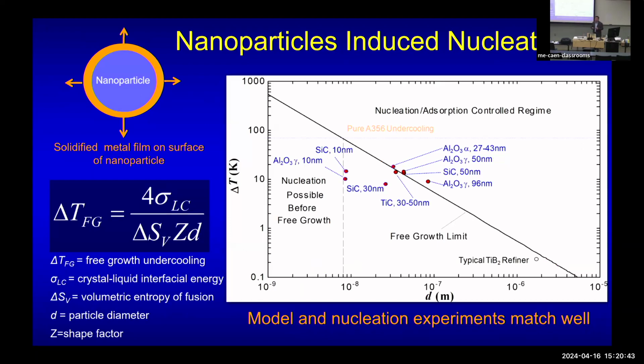And then it's fascinating, right? We studied how nanoparticles compare to the traditional microparticle-based grain refiner, because the most traditional grain refiners are based on particles of about 1 micrometer to 6 micrometers. They're very effective. They're already used in industry very effectively and inexpensively, right? So we studied nanoparticles compared to the microparticles. We found actually we are not as good as them, because we need much more undercooling: the smaller the size, the more undercooling they need to solidify, to grow the solid crystal. So on the surface, it looks like nano cannot win.